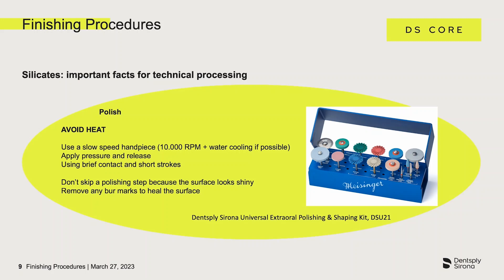The polishers should only have brief contact with the material surface and short strokes should be used. If the material is only polished, it is of the utmost importance that the surface is cured and compacted by the polishing process. At the end of polishing, the surface should appear smooth and shiny. To achieve this, it is usually sufficient to work with silicone polishers in descending grain size. Some manufacturers offer special instrument kits for the most time-saving and efficient surface finishing.